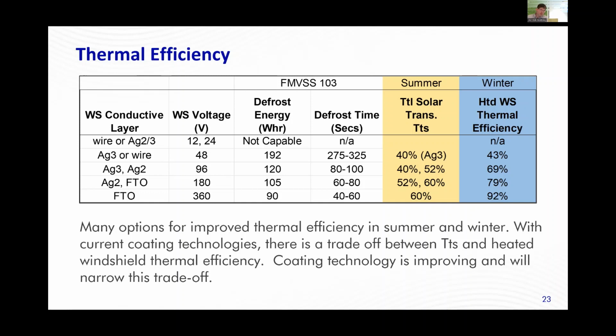But this is a good way to think about some of the trade-offs in terms of the different coating technologies for the windshield versus the potential thermal efficiency that's possible. I'll also note that the coating technology is improving and will narrow the trade-off. Either let's say, very good solar transmission or TTS values of, let's say, 40% that triple silver offers, the thermal efficiency in wintertime is lower. But if we look at the bottom of the chart, something like fluorine tin oxide can offer very high thermal efficiency, but the TTS is lower at 60%. Or the solar energy gain is higher at 60%. Sorry about that.